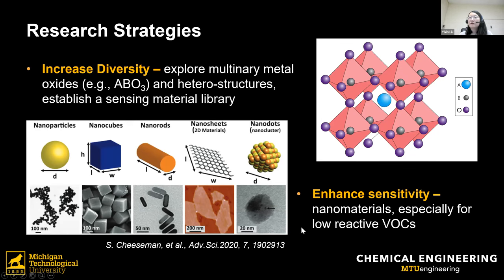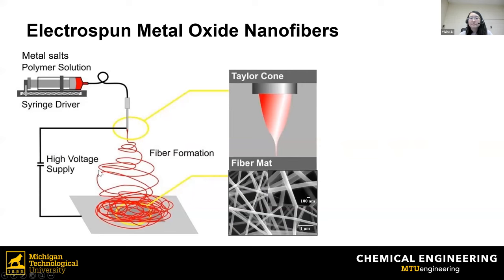So in our lab particularly, we work on electrospinning. We dissolve the metal salts in a certain solvent and add a polymer, and we mix the metal salts and polymer with the solvent together to form a polymeric precursor solution. Then we load it in a syringe connected with a small metallic needle, and we apply a very high voltage, usually 20 to 30 kilovolts, between this needle and a metallic conductive collector. That high voltage will drive the polymer solution and eject nanofibers. So we get those polymer nanofibers.